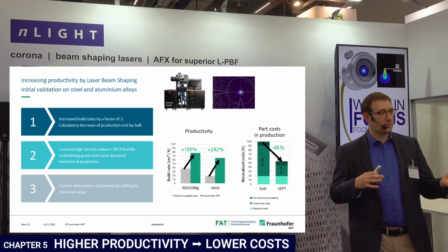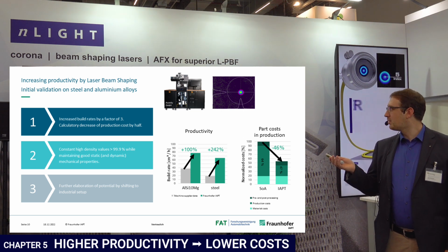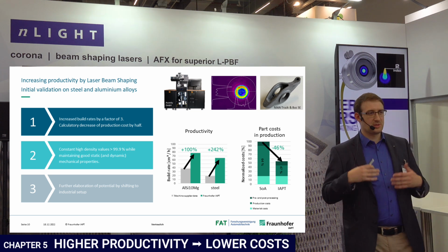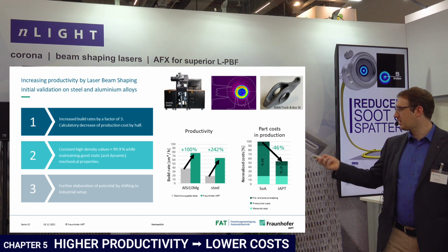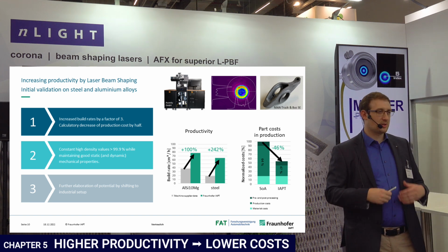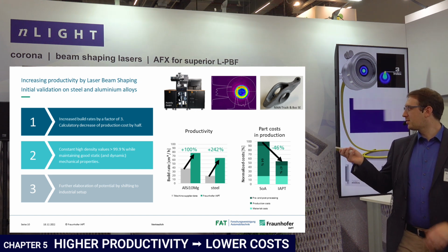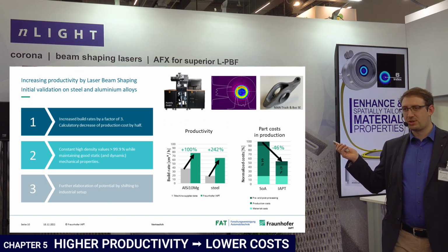For AlSi10Mg or aluminum alloys that worked, what about a steel alloy? So we used our lab system and looked at steel and found similar results. Even more impressive, if you see in the middle graph, we could increase the productivity by 240%. And for this particular part in the top right, the cost estimation is about minus 46%.